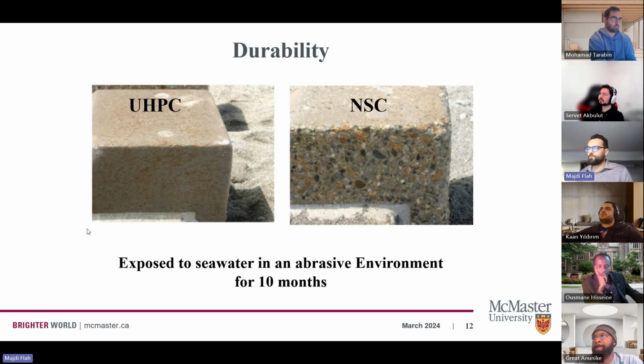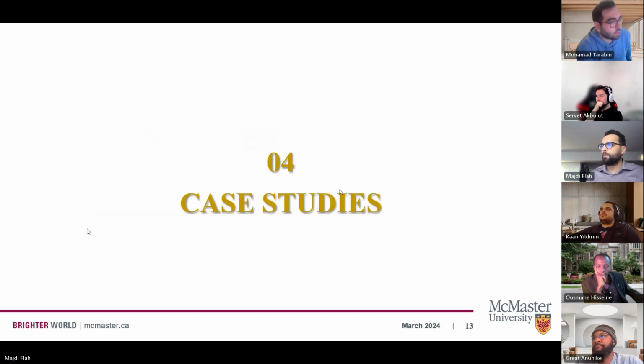Sorry. So that's the difference between UHPC and normal strength concrete. And these are two specimens having the same dimensions, being exposed to seawater in an abrasive environment for 10 months. And you can see from the normal strength concrete that there is some scaling there. And it really looks bad.